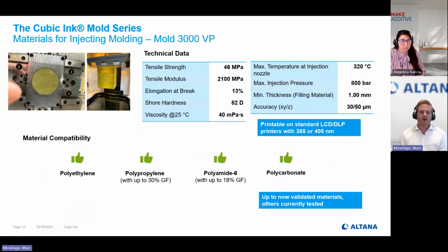Additionally, I'd like to also present one of our newest materials we developed for injection molding. This is our Mold 3000 VP. Also, here's some technical data on the top. Here, it is really necessary that the material has significant tensile strength and rigidity because the material is not allowed to bow. The conditions in injection molding are pretty harsh in terms of temperature and pressure. The material cannot bow to a certain extent. And nevertheless, the elongation at break is not very high, but you need a certain elongation at break, again, to avoid cracking. Viscosity here is 40 millipascal seconds, comparable to the other one. Low viscosity allows for a good accuracy of the print.